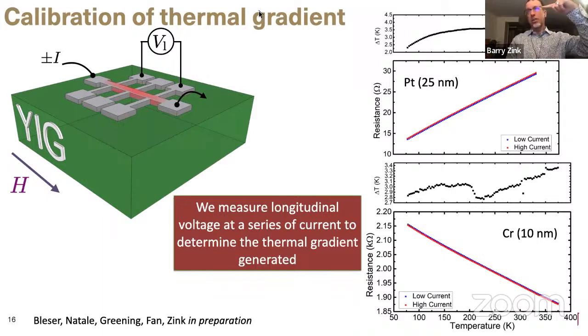That's where the high current is, and then a much lower current in that experiment. So the idea is that the metal Hall bar is in the same thermal state as it will be in the experiment when we switch the voltage around and do it in the transverse case, so that we know what the average temperature of that metal structure is when we drive a given current through it. We literally measure it in both cases, and then we know what the temperature should be.